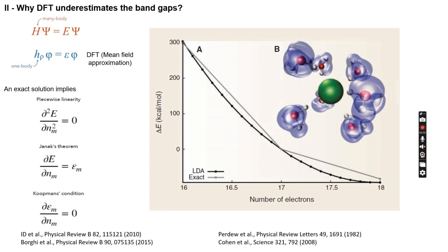That means that the energy of an orbital would be a function of its occupation. Therefore, in general, in DFT, electrons tend to be unstable. They are destabilized compared to the actual situation, meaning that it is too easy to excite an electron by photon interaction, which leads to band gaps that are lower than their experimental counterparts.